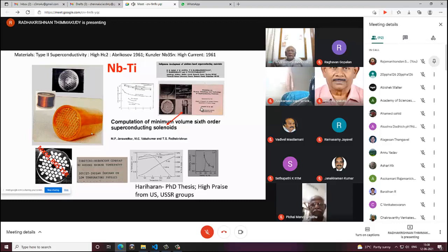But two important developments: Abrikosov gave new hope to find new materials that are type 2 superconductors with very high critical fields. And Kunzler, another IBM physicist, made niobium-3 tin in different metallurgical states, and produced very high current of the order of 10 to the 5 ampere per centimeter squared. It's a very large current density; a typical copper wire you have may carry maybe 100 ampere per centimeter squared. So you have several orders of magnitude larger current possible in superconductors, and these two discoveries got many people working, metallurgists joining the race, and of course we in Kalpakkam and BARC together had our own share of research, and we produced niobium titanium rods.